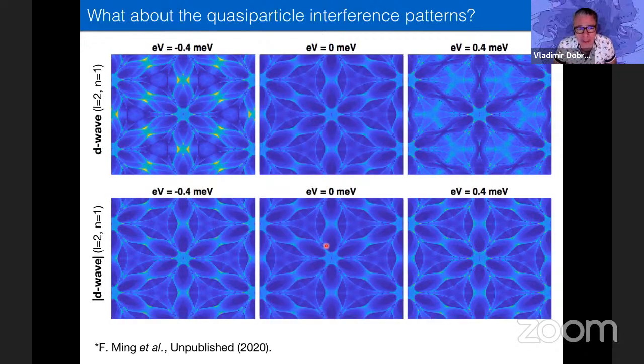So my question is, in this material, I understand that people have done extensive Hubbard model calculations, DCA, and so forth. So there are two questions related to that. The first one is, how important are the cluster corrections? Because in some materials like Mott organics, which are also on the triangular quasi-2D lattice, it seems that the cluster corrections are not so big, and that a lot can be explained through ignoring cluster corrections, using the single site version. Second question is, how large are the renormalizations?